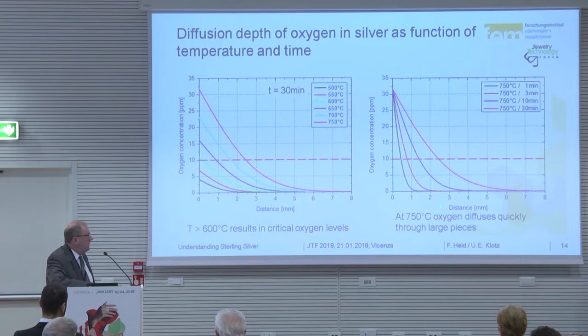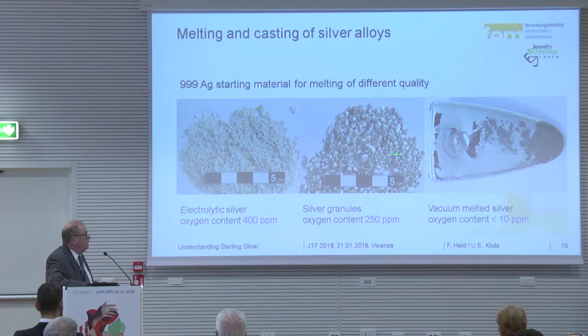If we look for ring shanks, it's around this size. So in a very short time, oxygen can pass this. This was the material we use for tests, beginning with electrolytic silver, the oxygen content is around 400 ppm, which is very high. If we use granulation material, oxygen is about 250, but depending on the granules, it could be